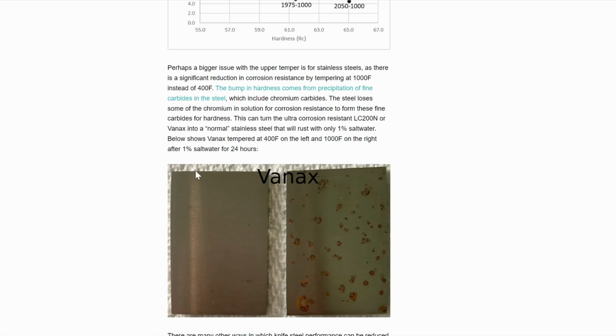So the one on the left was tempered at 400 degrees Fahrenheit. The one on the right was tempered at 1,000 degrees Fahrenheit. And when I sprayed it with 1% salt water, the 1,000 degree Fahrenheit one got rust spots on it, which performs more like a normal stainless tool steel, you know, something like S30V, which shows similar behavior. So you can take your Vanax and go from super corrosion resistance to low corrosion resistance by tempering in that range. But this tempering practice is actually quite common.